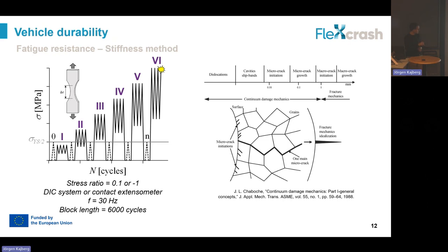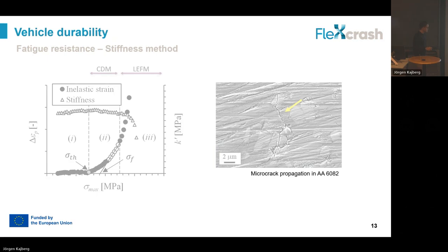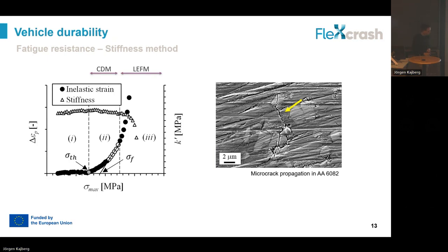parts here, and we are monitoring the elastic response of the material, the strain response of the material to a given stress value. So at the end, we can monitor how the damage is evolving, from the start of the fatigue damage to the micro crack initiation and propagation, and finally to the macro crack initiation and propagation. So the point is that at the end we get this kind of graph where we have this plastic strain related to this fatigue damage that we are monitoring by using this test. And we can plot this damage against the stress applied in each one of these fatigue blocks.